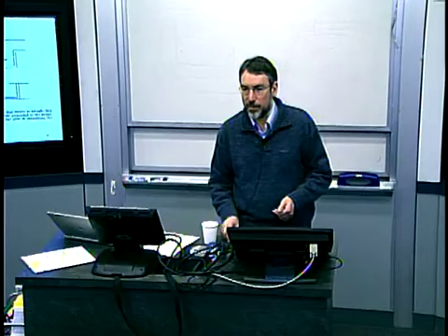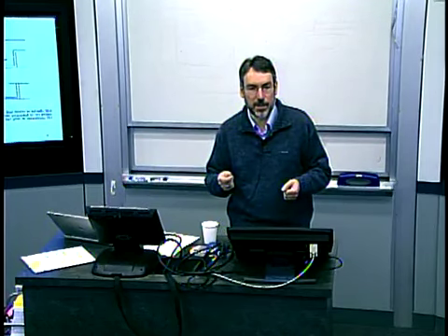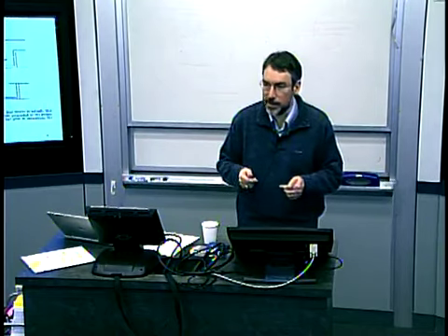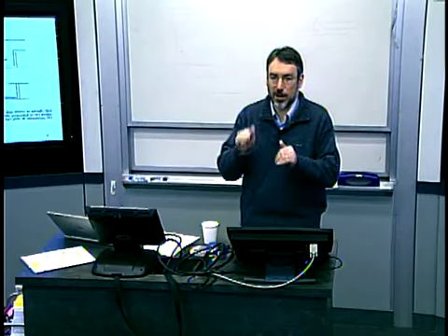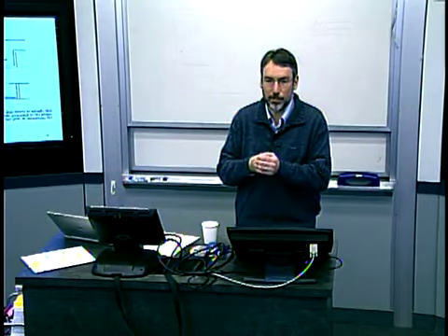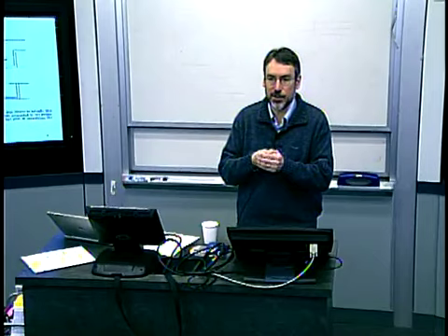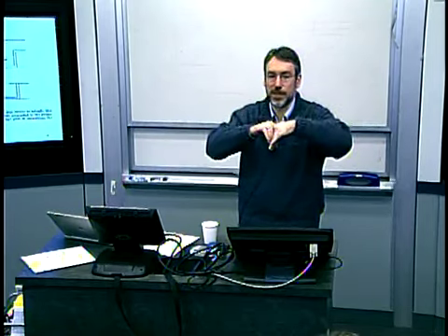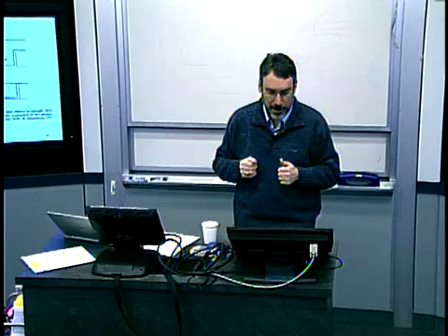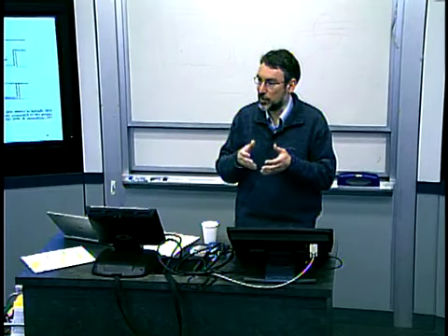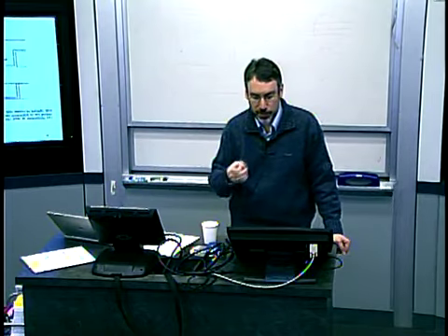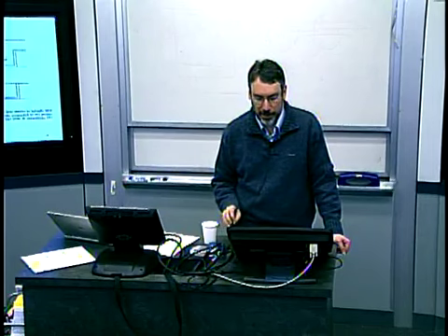The examples drawn from this paper talk about tungsten plugs in conjunction with aluminum interconnect, and they're actually mostly focused, I think, on tungsten contacts, with the idea that in older technology you didn't need to drill and form separate plugs between layers. You could just allow, say, an aluminum deposition to go in and fill that layer, and then etch off where you didn't want it. With scaling, it became pretty much essential to be able to form the plugs separately from the interconnect. So then tungsten was used to fill those plugs between metal layers as well.